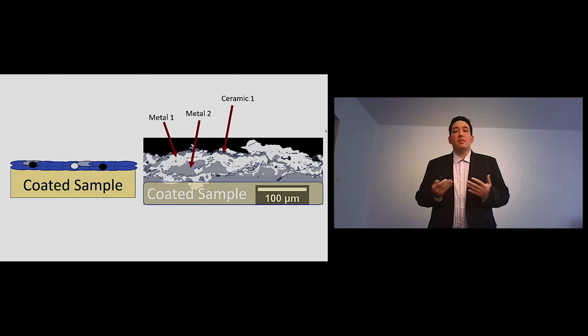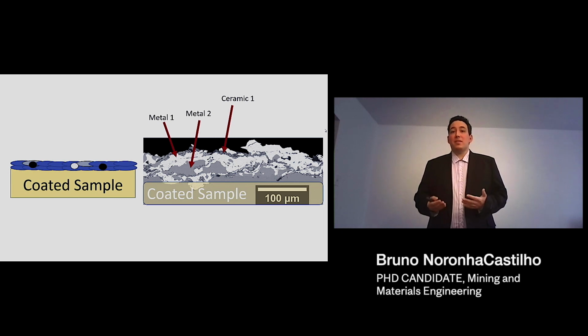However, we noticed that we didn't find the ceramic 2 that's supposed to be there. Furthermore, the coating had really bad properties like mechanical strength, adhesion, and cohesion between the particles. The last problem that we have is that the coating is really thin, indicating a really bad deposition efficiency. So based on the lack of the second ceramic, because that one is the one that has the highest melting point, we thought that maybe what happened is that the stream was not hot enough to melt all the particles.